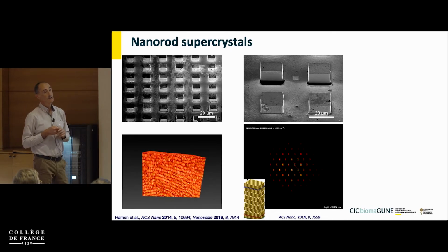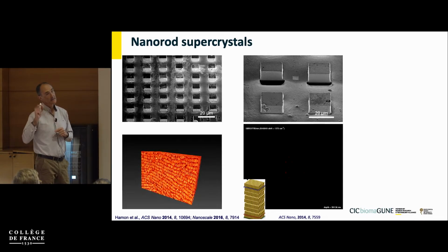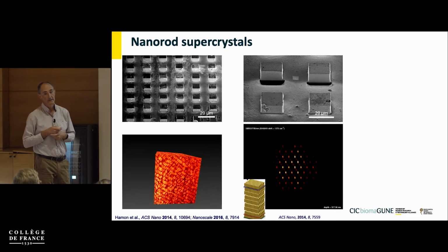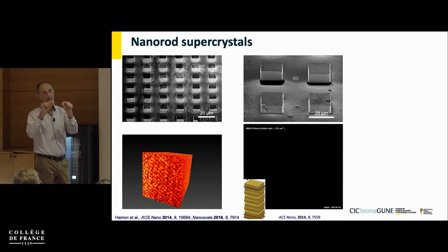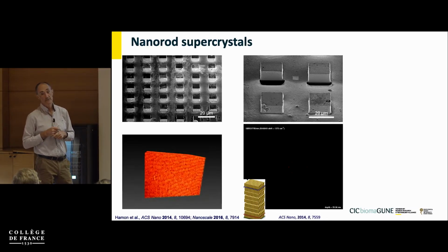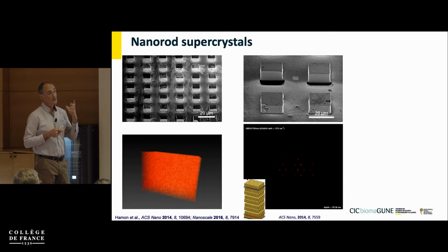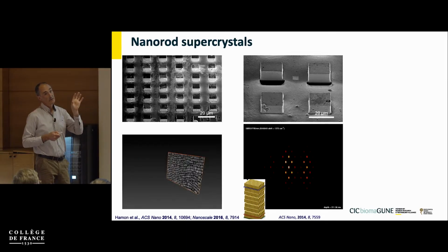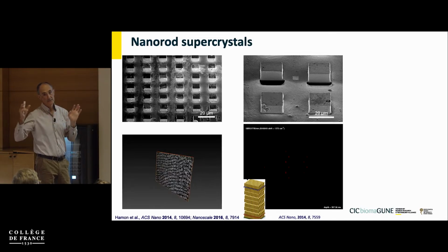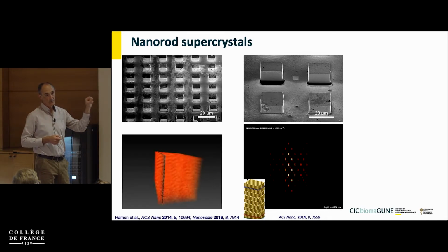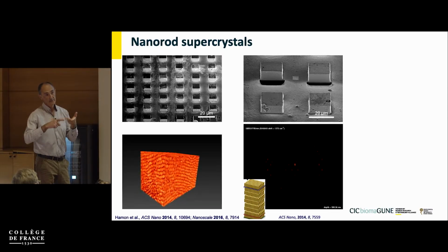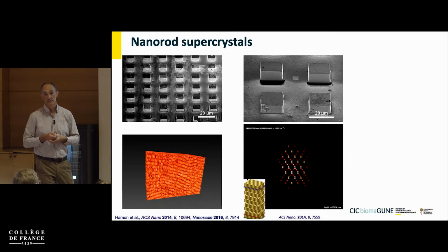But we were so lucky that the silica, the mesoporous silica, was actually infiltrating the multilayers and creating little gaps between the monolayers with mesopores through which the analytes could diffuse. And not only that, the small metabolites that the bacteria used to communicate with each other were able to diffuse through the pores, but the pores were small enough that proteins, lipids, and other bigger molecules could not diffuse inside.